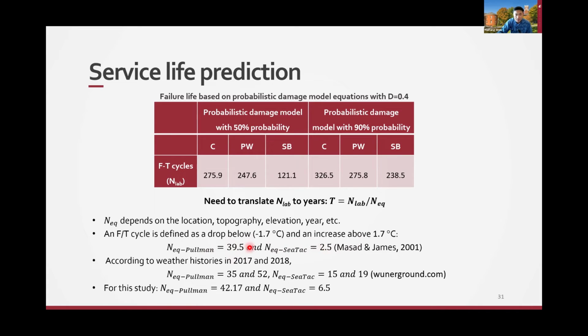We studied another database, and they predict a slightly different number of freeze-thaw cycles for the west side and east side. So on average, we take the average, right? For the east side in Pullman, we take an average from different studies. We take about 42 cycles of freeze-thaw a year versus only about 6 or so on the west side. And you will see the number of cycles for the west side and the east side, and also for different probabilities, 50% and 90%.